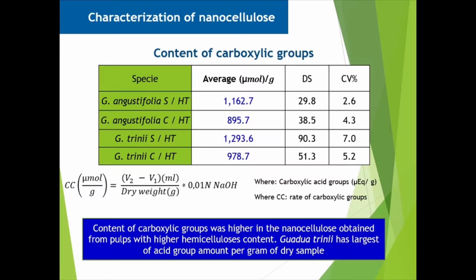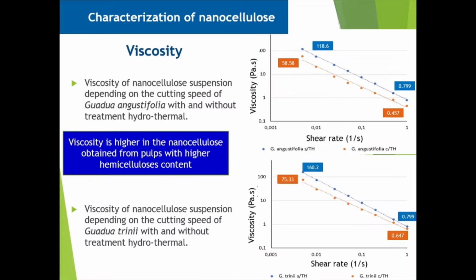Carboxylic groups were obtained through conductometric titration. The amount of carboxylic groups per gram of dry pulp indicates the degree of oxidation with the TEMPO treatment, since they generate repulsive force among themselves, which favors the nanofibrillation structure, and this is higher in both species in pulp that did not undergo hydrothermal pretreatment.